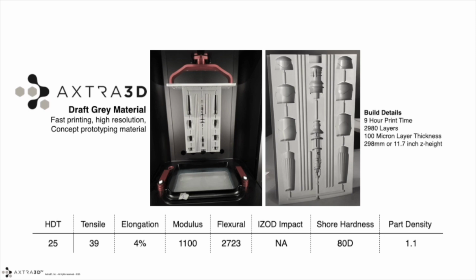This material isn't really impressive from a mechanical perspective. It sits there with an HDT of 25, tensile strength of 39 megapascals, pretty low elongation at 4%. But the reason we love this material is because it's incredibly accurate. The surface quality is second to none, and ultimately, for concept modeling and draft prints, this is a great material just to get the maximum value out of our light engine technology.